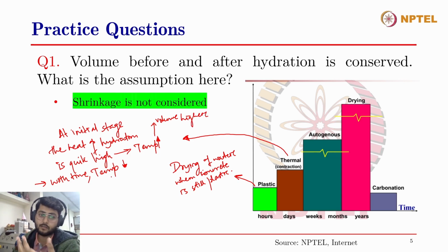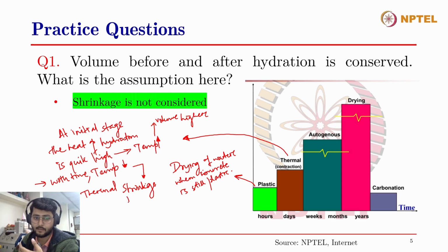But when the temperature is reduced, the concrete has cooled down, and it has been several days after the casting. Now that the concrete has cooled down, the expanded volume wants to contract. So there is a shrinkage. And since it has been several days after the casting, the concrete has hardened. And now that it wants to undergo a shrinkage, there might be cracking in the hardened concrete due to thermal shrinkage.